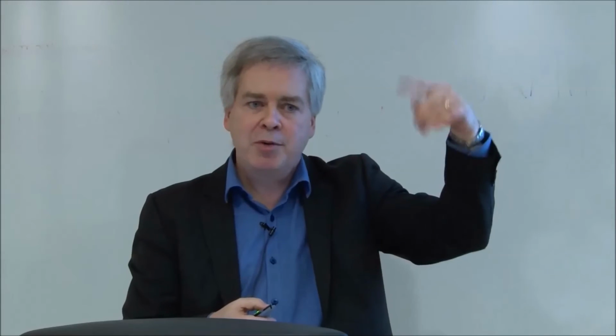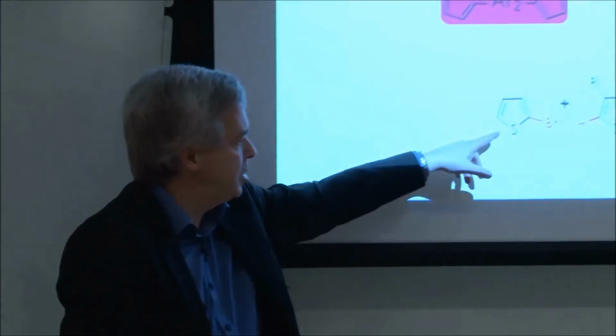So I gave you the first explanation that you will find in the literature. I'm not sure it's the right one. Okay, so I just reported what is. If you read it, they will say that branching will increase as a function of the molecular weight, and it could be that reason. It could be the stability of the catalyst, making side reactions and cross-linking. It could be also the stability of the bromo. And when it becomes insoluble, for the soluble material, we think it's related to the fact that we reach a too high molecular weight.